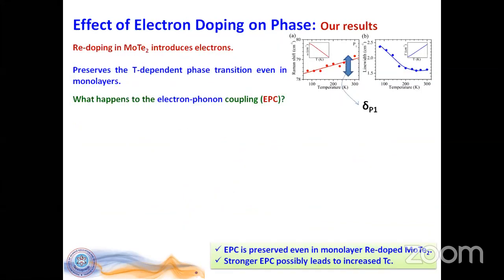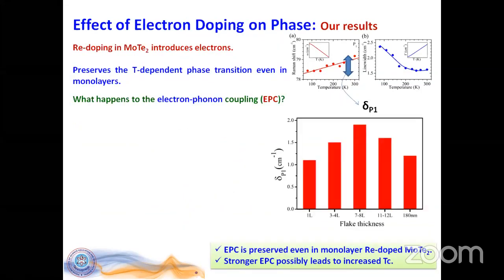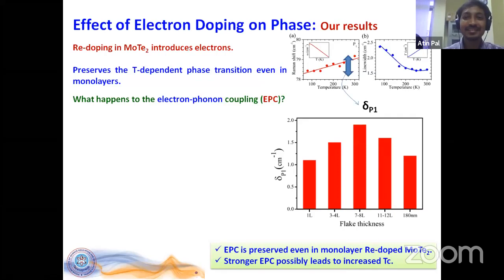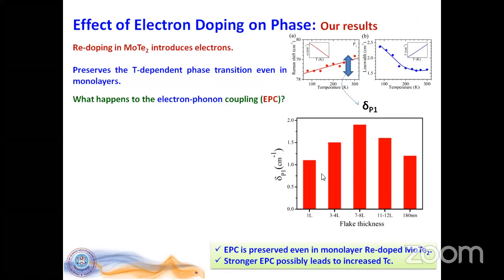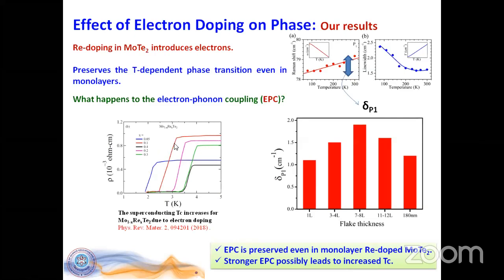And now we look at the rhenium-doped system, and almost done. In the rhenium-doped system, this electron-phonon coupling prevails down to 1 layer, and that could possibly also be connected with the increase in the superconducting temperature, so probably this electron-phonon coupling is connected somewhere.